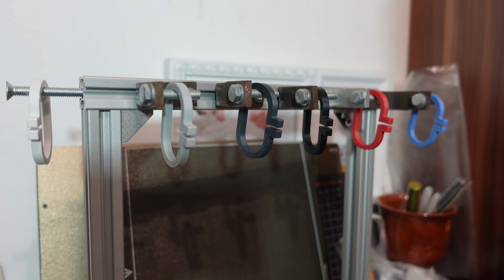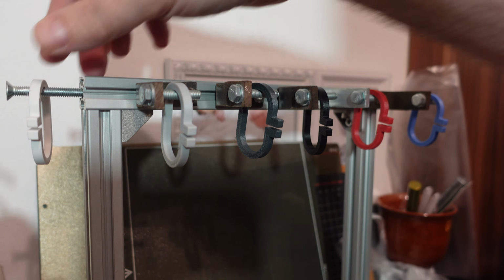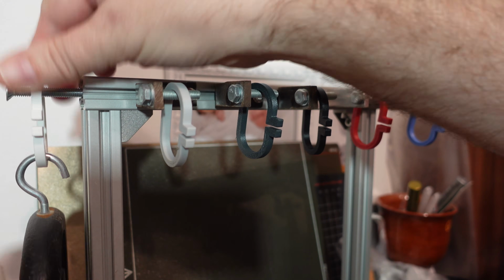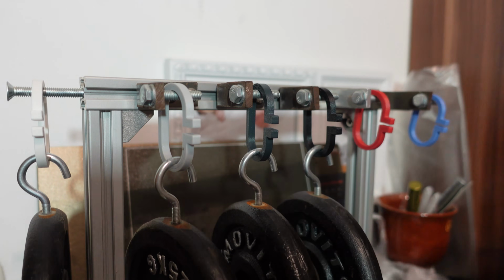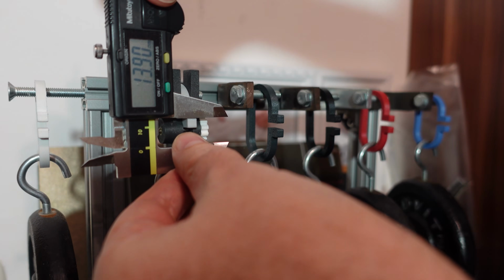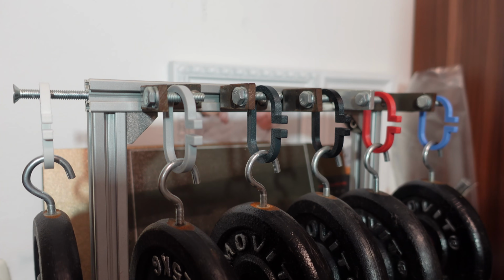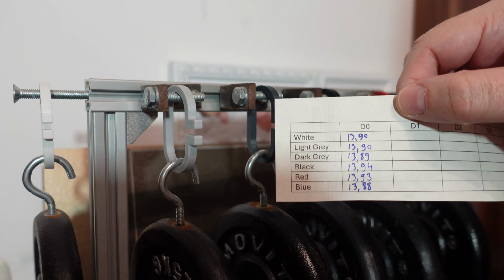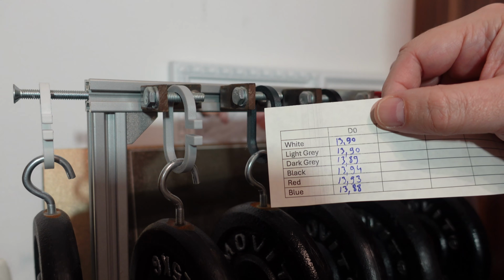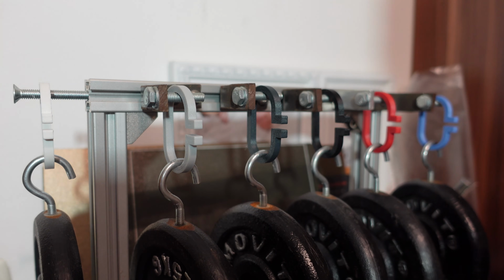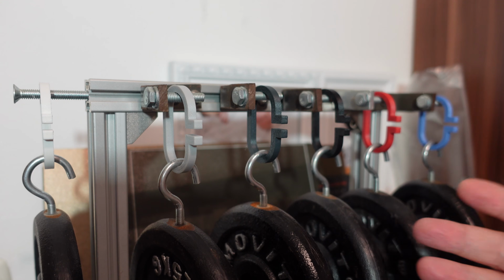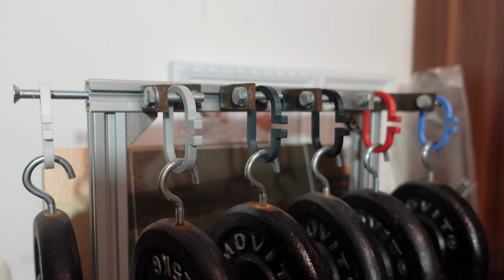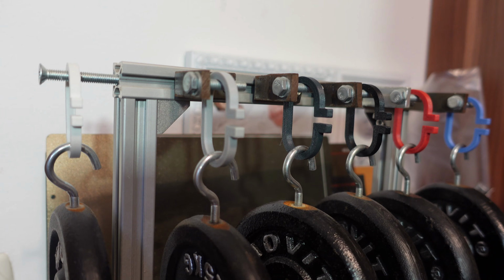Creep has a deformation under constant load. It's a little bit hard to have everything in one frame. Load is 1.25 kilograms. Too many colors to measure all of them in front of the camera, so they are all measured, and the good news is that there is no big difference between the colors. The creep test is the first one I'm starting with because it's the longest, and then in the meantime I'm doing other tests. But let's jump 5 days. Day 5, so far very similar deformation and very low creeping.